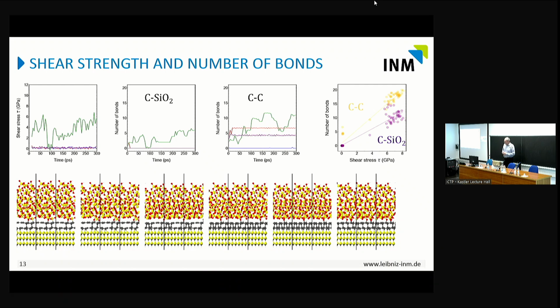And there's one important observation. I have to walk you through this transparency here. So on the upper left, you see the shear stress as a function of time, so when we start scanning. And on the second graph, you see actually the number of bonds in 5 different trajectories. It turns out we have to do simulations with different silicon oxide configurations, because it depends very much on the details of the structure of the amorphous material what happens. But what we can see here is that the number of carbon silicon oxide bonds is absolutely congruent with the shear stress.